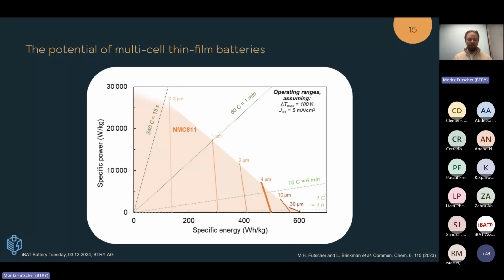And here you can also see the C rates corresponding to that in green. And here you can see that, especially if we now look at the most part here is below 6 minutes, so above 10 C in C rate. And in green here, you see the line for 1 minute as well. And indeed, it's possible to fabricate a battery which can be charged in 1 minute, still having a high specific energy and specific power.